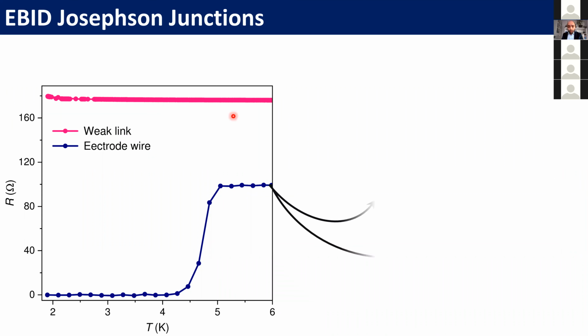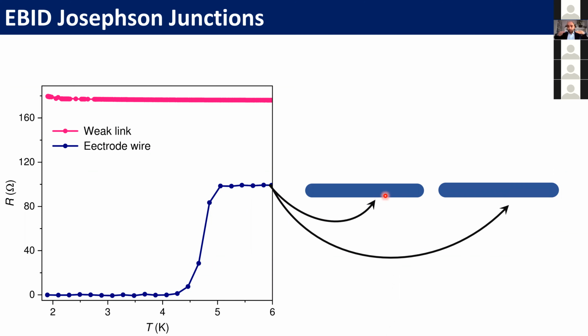So we first deposited 2 superconducting electrodes that were separated by about 150, 160 nanometers. And then we connected them using this normal metallic weak link, which was deposited at a faster rate. So it wouldn't become superconducting on its own.